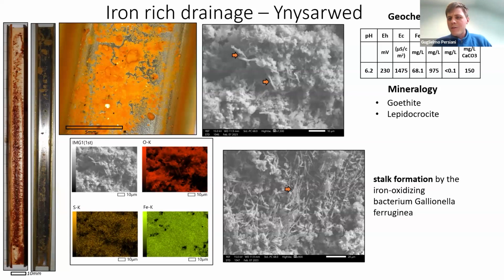The concentration of iron is about 70 milligrams per liter, and what this shows is that the minerals that fall on the surface are identified as goethite and lepidocrocite, which are two iron oxides. But still, we can see that even in this orange ochreous material, which is again the classic one, we can find a good amount of structures which are the result of microbial metabolism, such as stalk formation.